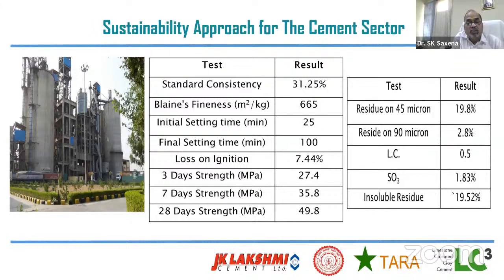And these are some of the test results which we achieved. The standard consistency or the water cement ratio, it was 31.25%. Blaine was, of course, on the higher side, which was expected, to the tune of 665 meters square per kg. Initial setting time was around 25, then final setting time was 100. Loss on ignition, it was expected, as it was 7.44%.